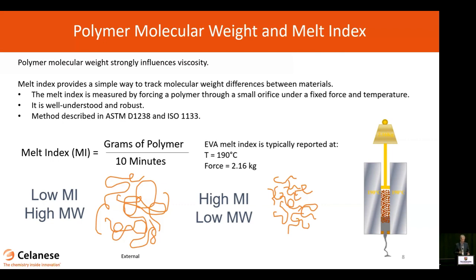So when you do a melt index measurement, you essentially take the polymer, you heat it up, and you put it in a barrel, and you compress it under a known load, and you force it through an orifice of a controlled size. And by measuring the flow rate through that orifice, you're able to extract information that you can relate to the molecular weight of the polymer. So again, the nice thing about this is it's a very reproducible measurement, very robust. Every laboratory should be able to get almost the same exact measurement on this kind of a test.